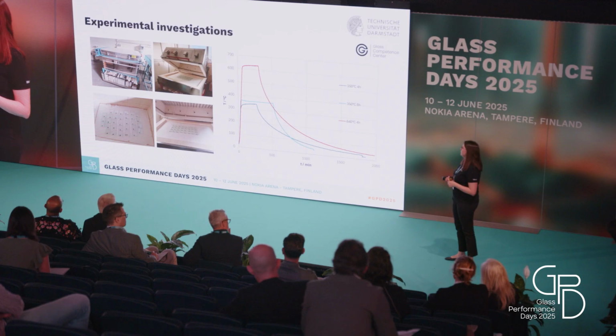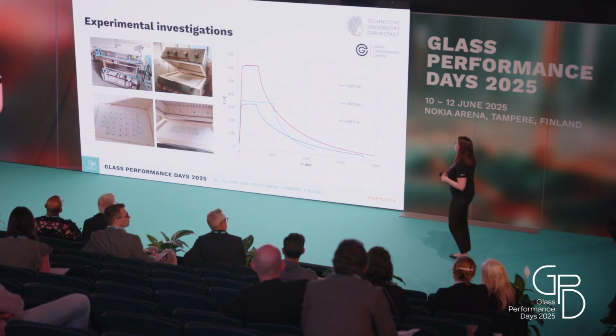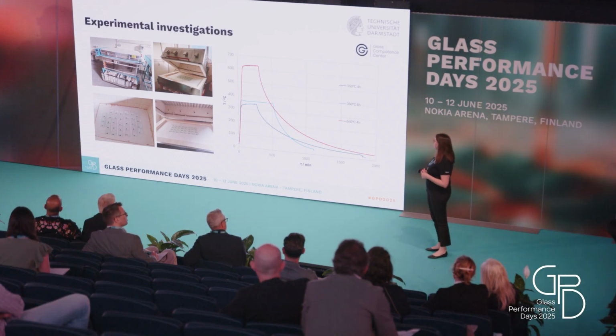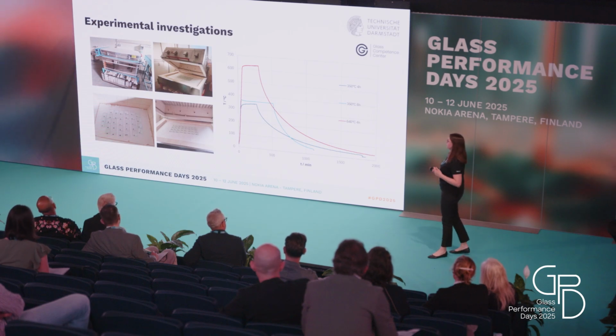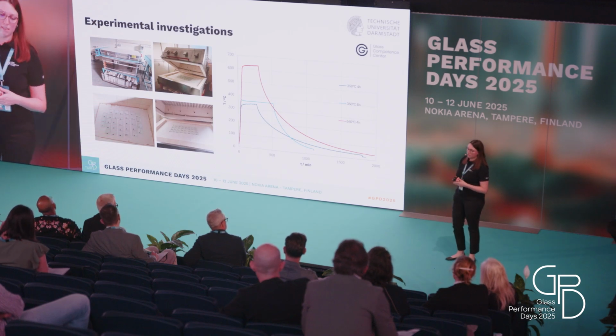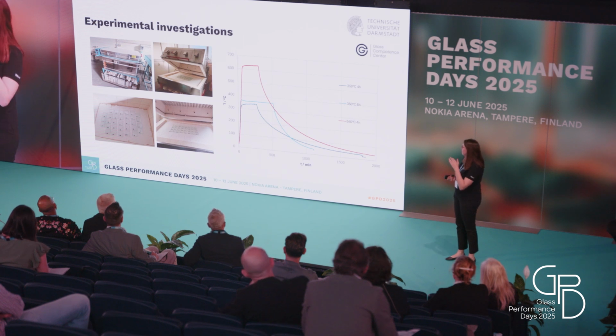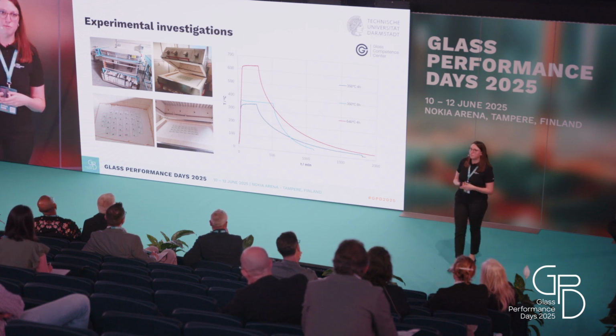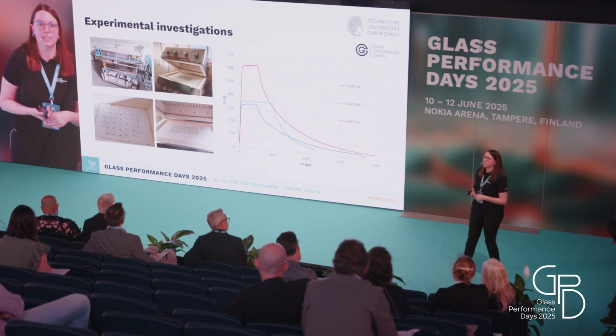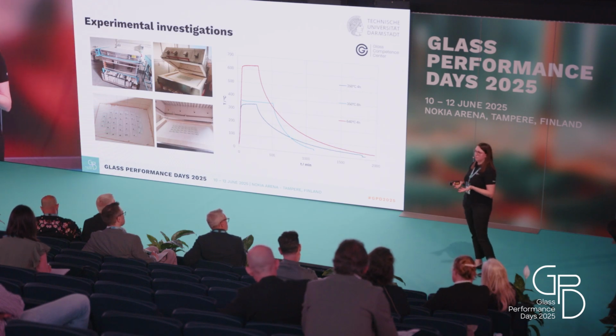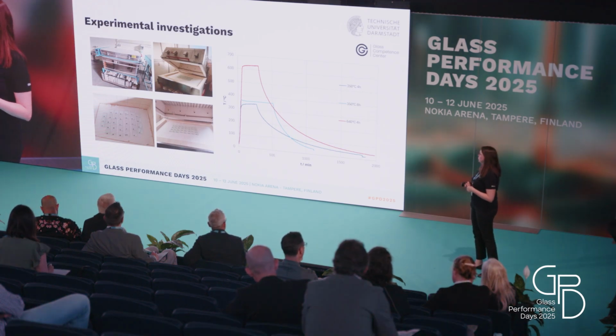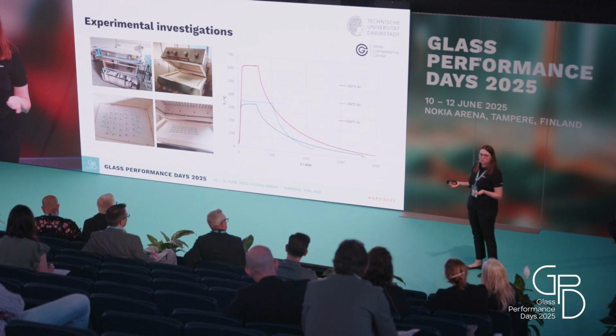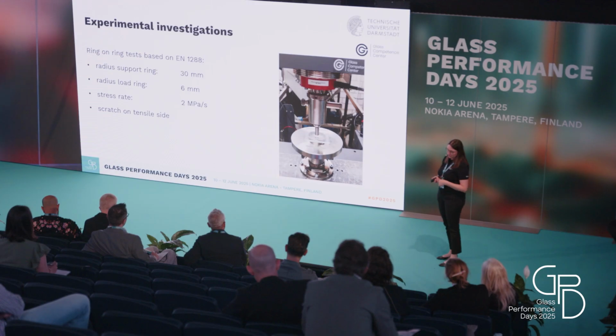For 3 series, we also had the possibility to record the time-temperature curves, and we see the results here. So the heating was always conducted with 10 Kelvin per minute. Then we had the heat treatment period, and then the cooling down was performed very slowly, just to guarantee that our samples are still annealed after the treatment. And we also checked this with SCALP measurements, so this was effectively also the case.